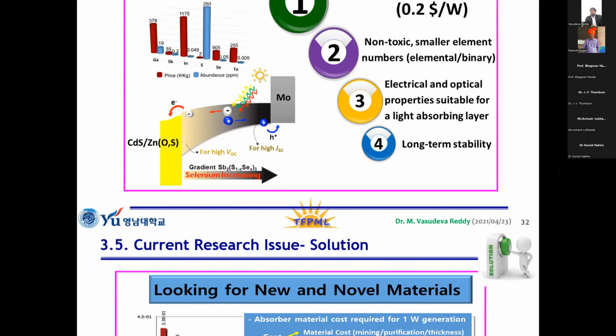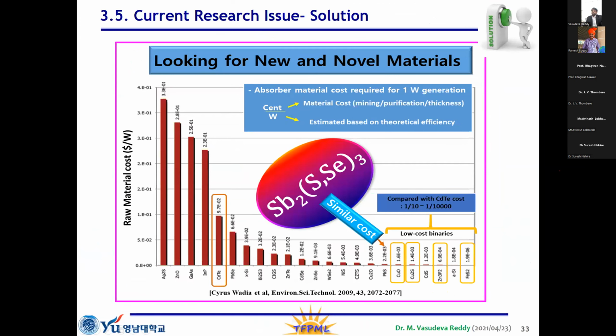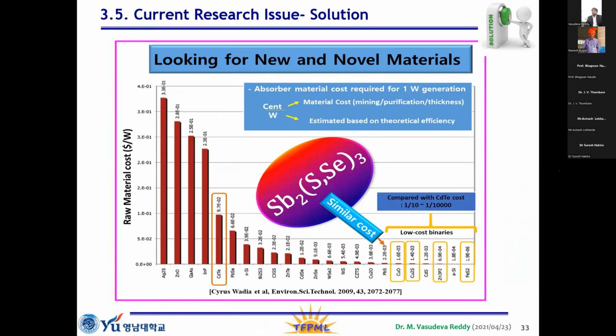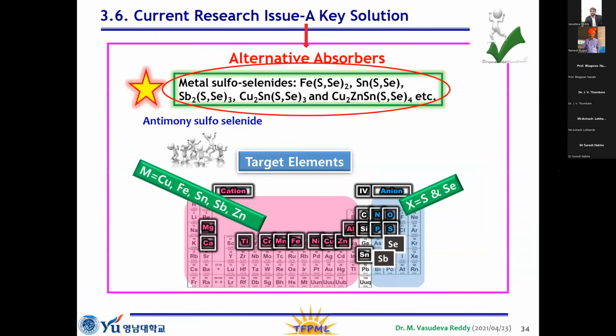So you can simply refer to that article, and we can focus on this side where we can get the low cost materials, and we should choose from these generic low cost materials. Particularly here I am going to show you the various alternative materials for the application, like iron based or copper based materials we can select. However, in copper based materials, the stability and other issues still exist. And in iron based materials, the purification and also preparing a single phase for solar application is challenging. Therefore, it is hard to focus on iron based or copper based materials. Therefore, the suitable materials are sulfosalt based materials or tin based metal chalcogenides, which are promising for solar cell application.